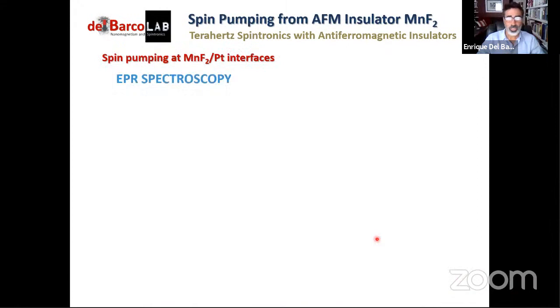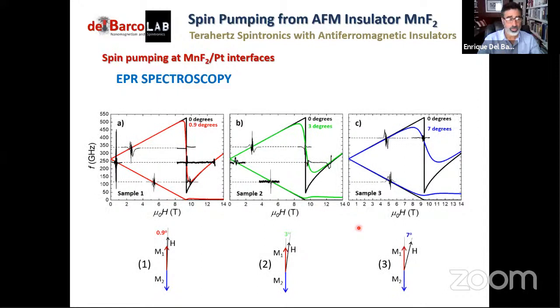All right, so the first thing we can do with this system is just run spectroscopy studies. And well, this is a little complicated because Priyanka had to go 5 different times to Tallahassee. The samples don't like to stay under the action of a magnetic field. So she had to repeat the experiment several times, ending up using, I believe, 12 different samples in 5 trips. So I'm showing you spectroscopic results on 3 different samples. The difference between them is that they were misaligned with respect to the direction of application of the magnetic field. In this case, very close to a perfect alignment, only 1 degree out. In this case, 3 degrees, and in this case, 7 degrees. But it turns out that this actually allowed us to study things that we wouldn't have been able to do if we had a perfect alignment. So it worked out pretty well.